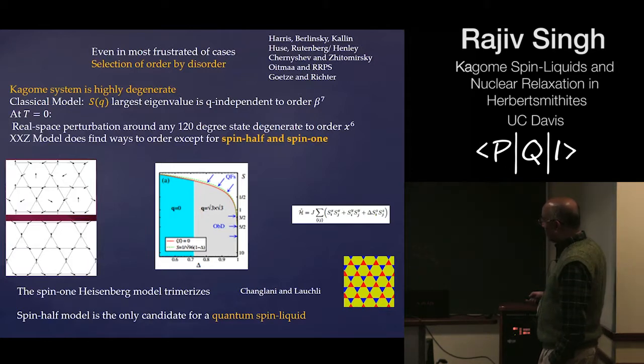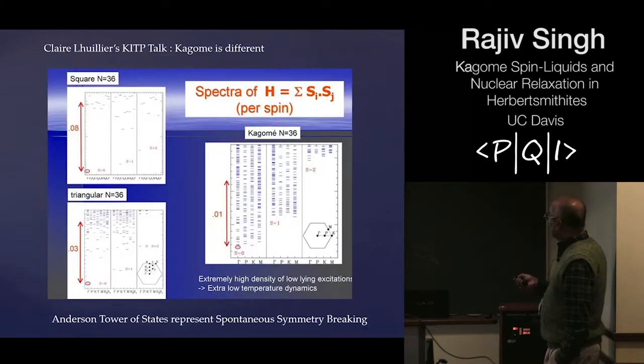And the phase diagram that we believe is correct really is that if this is an anisotropy axis, so delta equals 1 corresponds to the Heisenberg model, 0 corresponds to the Ising model, and S is the spin quantum number. So anything 3/2 and higher actually get ordered due to this order by disorder phenomena. The only thing that does not get ordered is spin 1 and spin 1/2, and in fact the spin 1 ends up trimerizing rather. It starts to form a different type of an ordered pattern where the down pointing spin have a different correlation from the up pointing spin. So really the spin 1/2 model is the only candidate for a quantum spin liquid,